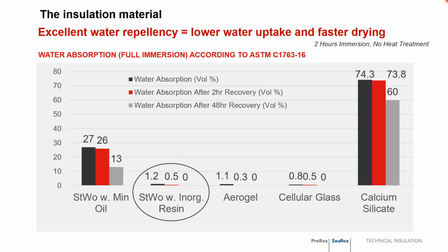These are the results from the full submersion test, and it details the water absorption characteristics of stone wool with 2 different types of water repellent additives in comparison to some other types of insulation out there. The absorption is measured in percent volume in this graph. Each bar corresponds to the amount of water absorbed and the recovery time. The insulations that absorb the least amount of water also recover faster because there is less water to dissipate.